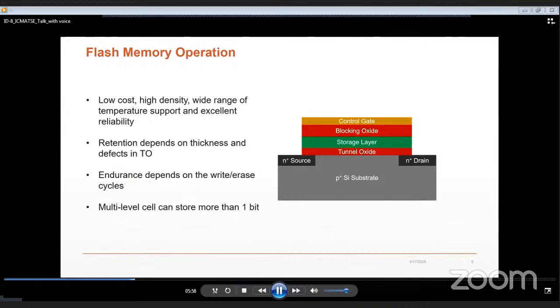A flash memory is a three-terminal device having the same structure as a MOSFET, but with an additional layer embedded within the gate oxide of the transistor, which is called the charge trapping layer. The layer in between the channel and the charge trapping layer is called the tunnel oxide, while the layer in between the charge trapping layer and the gate is called the blocking oxide. The tunnel oxide is usually thin and allows the tunneling of charges during the program and erase operations from and to the channel or charge trapping layer, while the blocking oxide is thicker and blocks the leakage of the stored charges to the gate.